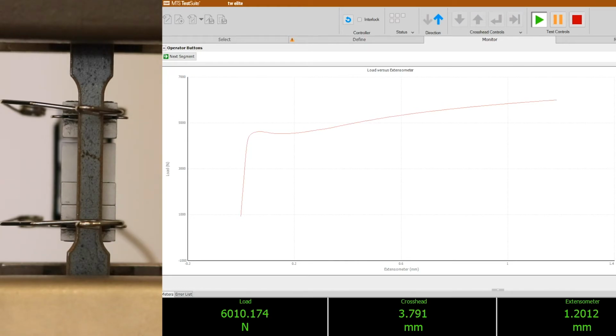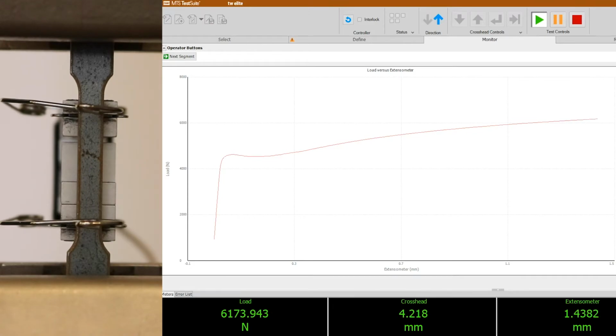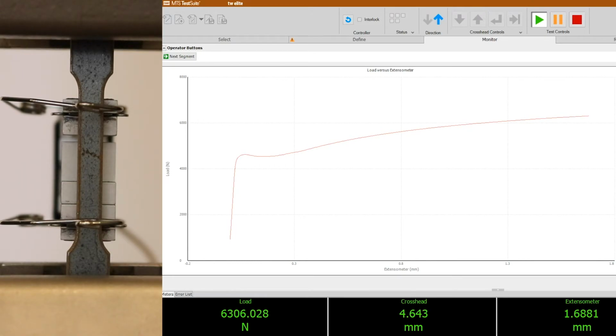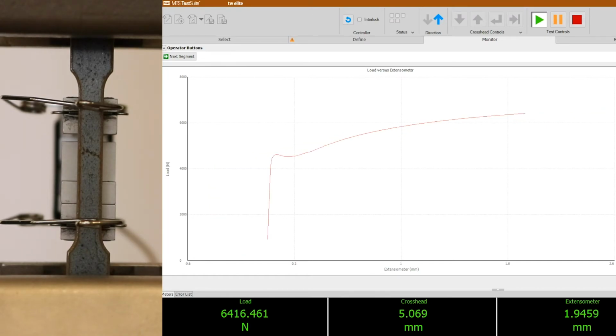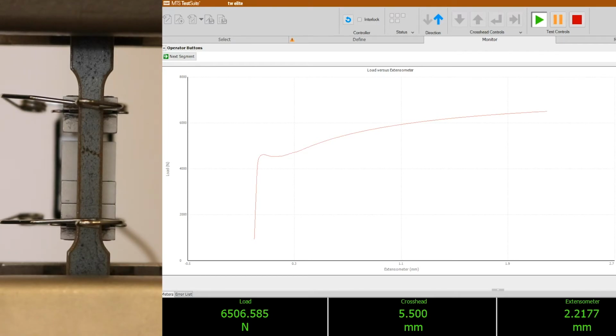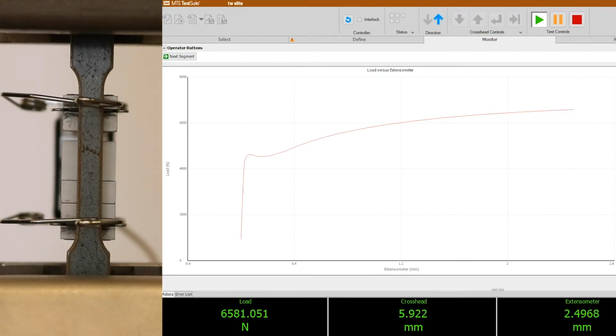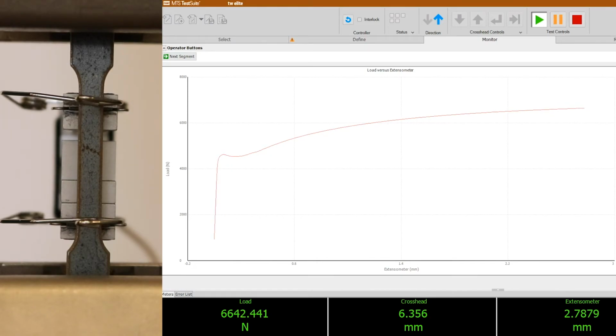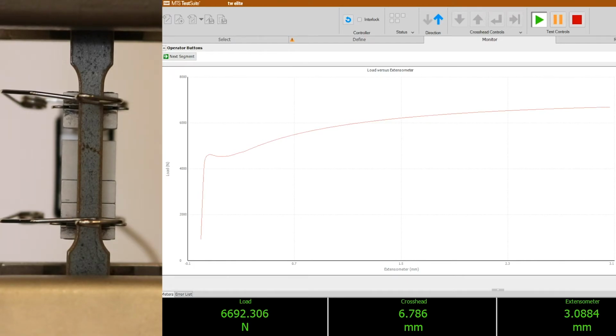And you can see down on the x-axis the amount that the sample has elongated by between the arms of the extensometer and the load that's being applied on the y-axis. So now we're up at about 6.4 kilonewtons now. So a significant amount of force being applied here. And as this curve continues to develop and the graph auto scales, you'll get an appreciation of just how small the elastic region of the curve is in terms of the steel's overall extensibility.